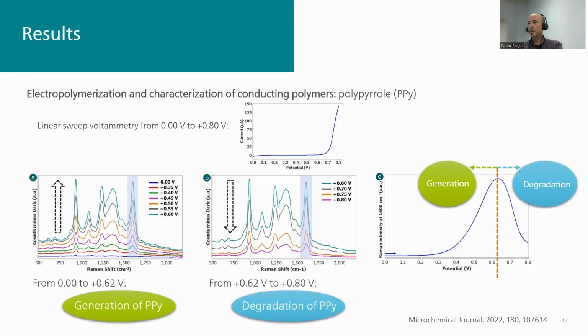Okay. So now that we have entered into the field of materials, and I have shown you some assays with nanotubes, I would like to remark also some assays with organic conductive polymers. This can be used for PEDOT, for polyaniline, but I will show you here, for instance, one assay with polypyrrole. In this case, you know that these organic conductive polymers could be generated in situ on top of the surface of our electrodes just by an electrochemical process. So imagine that we start with the pyrrole, with a monomer, with this electrochemical scan going from 0 volts to +0.8 volts. We would like to oxidize the monomer and to generate the polymer, the polypyrrole.